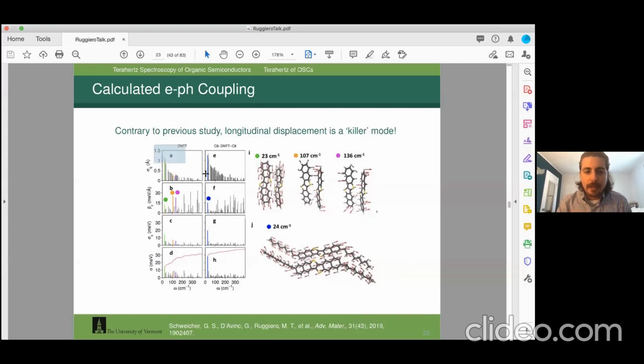This first 2 panels are just the amplitude of each vibrational mode on a mode-by-mode basis. And what we see is this 1 over frequency squared dependence. So as we increase the frequency, the amplitude in real space decreases quadratically, which is what we expect.